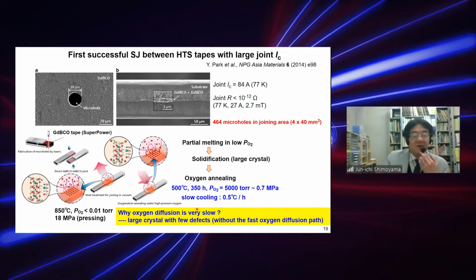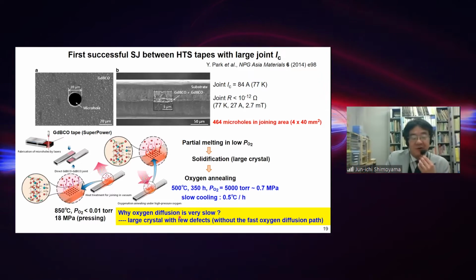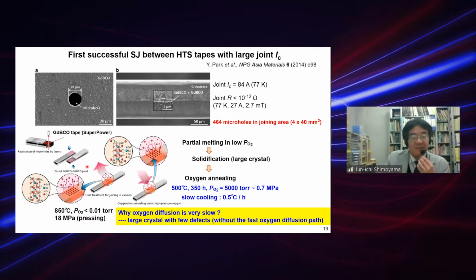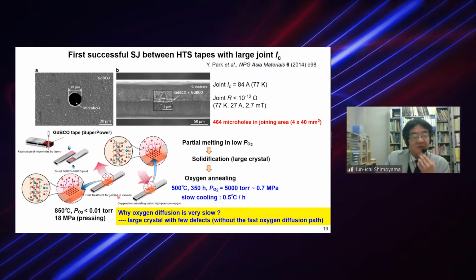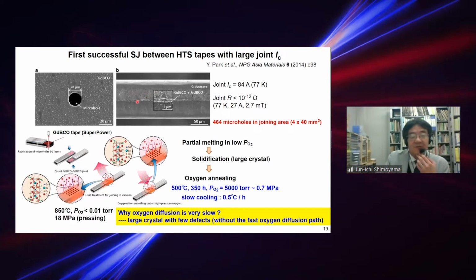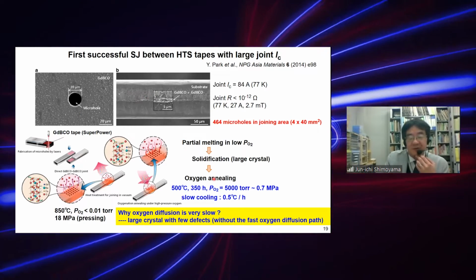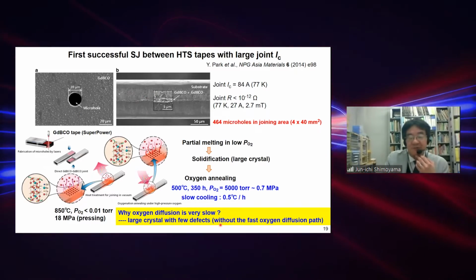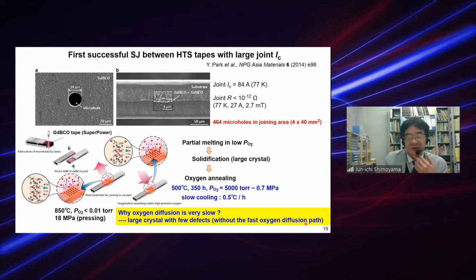So why is oxygen diffusion very slow in this case? Large crystals with few defects formed after melt solidification. This means that there is no fast oxygen diffusion path.